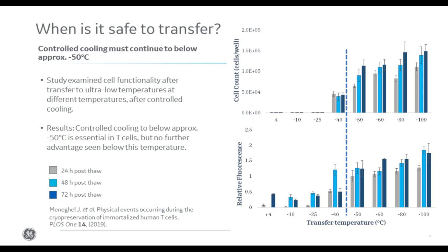Now, let's see at what point it is safe to stop the controlled cooling and transfer to long-term storage. Well, this is actually a problem that puzzled us for a while, as there didn't seem any consistency in the literature. Some groups, particularly with ovarian cells and eggs, would transfer to long-term storage below around -40 to -50 degrees. Other groups would cool until -80 degrees, especially those using passive coolers. Other groups considered that samples must be cooled below their extracellular glass transition temperature, around -120 degrees, before long-term storage. So we studied the literature, but couldn't find much firm data on this key point.